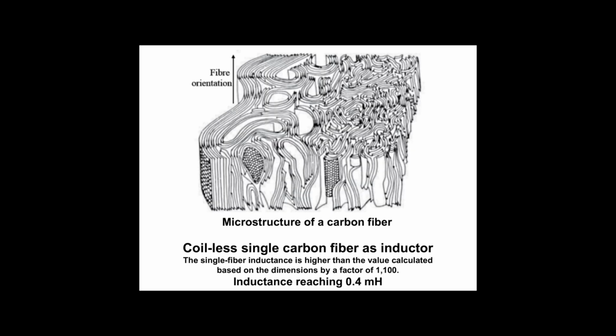A single carbon fiber has a cross-sectional morphology looking like this. It consists of carbon layers that are crooked, bent. And because of this nanostructure within a carbon fiber, even though the fiber is straight and coilless, the fiber can have substantial inductance. And we discovered just recently that the single fiber inductance is higher than the value calculated based on the dimensions by a factor of 1100. Okay. And the inductance reaches 0.4 millihenry with just a short length of the carbon fiber. Now, millihenry is actually a pretty high inductance.